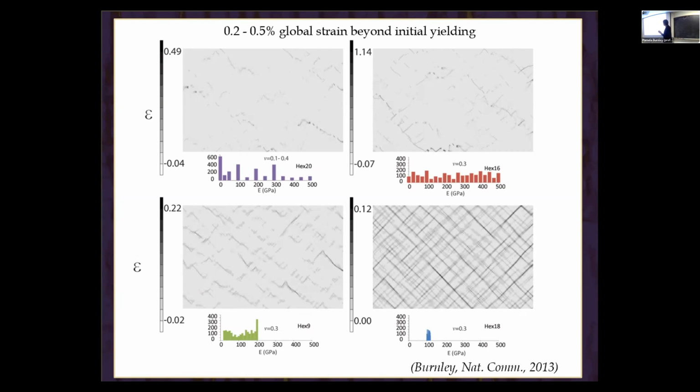And you see we have shear localization in all the models. But again, the density is different. We have a lot of shear localization here, but the amount of shear localization in the strain is small compared to up here. We have a lot of shear localization on a small number of planes, right? And then these models basically fail. I get too much shear localization, they can't go. So again, we have this difference in the patterning of shear localization, which is a function of the force structure, right? The force structure is the foundation for how it's going to shear localize.